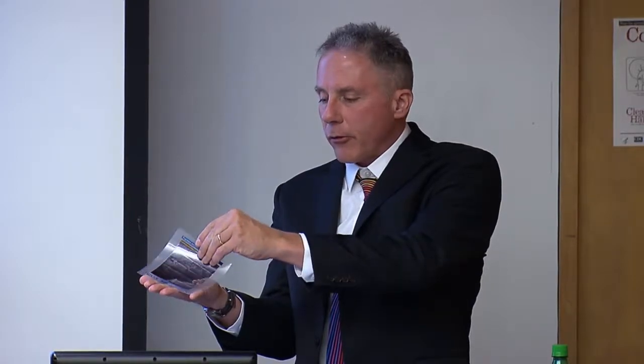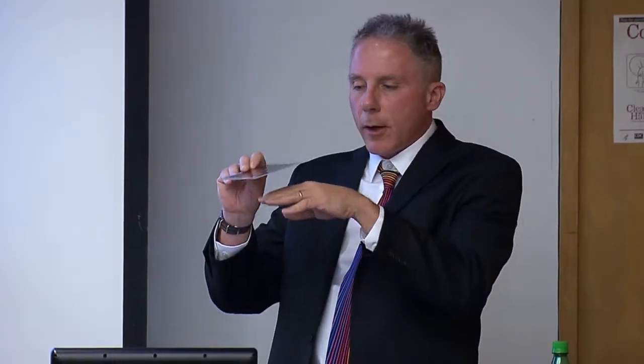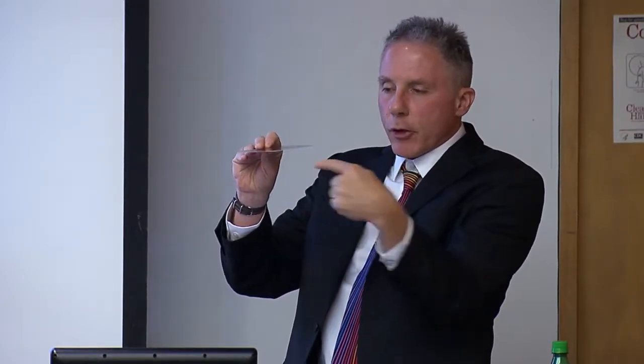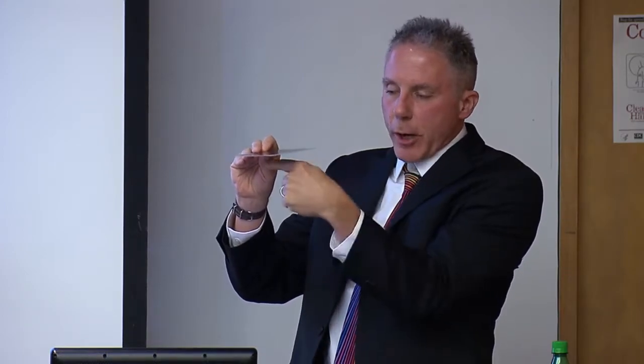So we developed a process for peeling off the solar cells using a process that's very much like peeling Post-its from a Post-it note. It involves using a sacrificial etch process to etch away an aluminum gallium arsenide layer that yields a single crystal, and in fact it's held in compressive mechanical stress, as I was talking about with you, Frank, earlier, by lamination onto a metal backplate, so that when I flex it, it doesn't crack, and it's very lightweight and flexible. This is a 27% efficient solar cell.